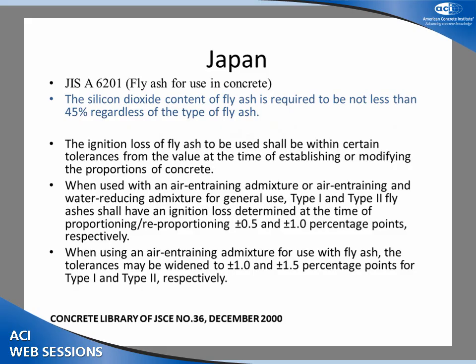One of the things I got out of the Japanese standard, actually, is a report that Professor Nagataki wrote some 10, 12 years ago. They have a requirement that the SiO2 content of the ash, regardless of the type of ash, has to be at least 45%, which I thought was interesting. And then when you use it in concrete, you take the LOI of the fly ash you use to establish your mix designs, and it's not allowed to vary by more than about 1% either way if you're doing reproportioning during a job. That's why they control the LOI of the ash. You establish a base LOI, and then you have to stay within the limits of that. So I thought it was an interesting way they approached that problem.